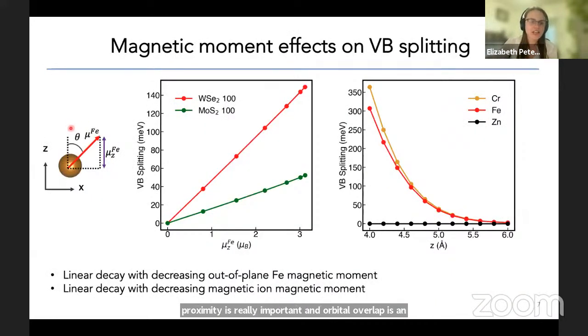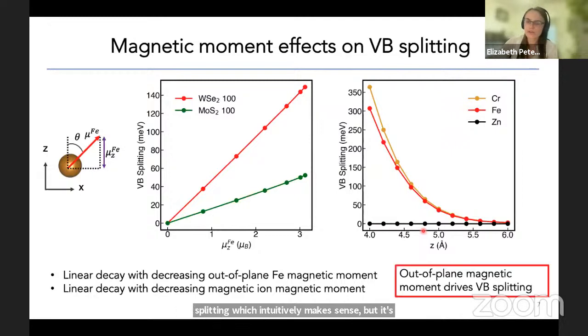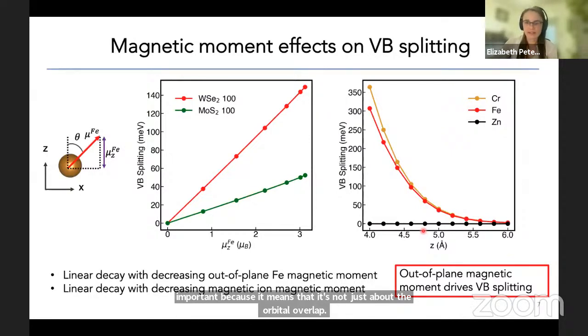So the next knob I can turn is I can change the out-of-plane magnetic moment of the iron atom. And so I tried rotating the magnetic moment from being fully out of plane to being in plane. And what I see is a linear relationship between the out-of-plane magnetic moment of the iron atom and the valence band splitting. And this immediately makes you think of a Zeeman effect, that there is clearly something Zeeman-like about this phenomenon. I can also change the atom from iron to chromium, which has a larger calculated magnetic moment and indeed has a larger valence band splitting. And it actually scales just about linearly with the increase in the magnetic moment. Zinc is a filled d shell non-magnetic material. So I tried zinc as well, and I got no valence band splitting, which intuitively makes sense, but is important because it means that it's not just about the orbital overlap. The out-of-plane magnetic moment is a big driver of the valence band splitting.